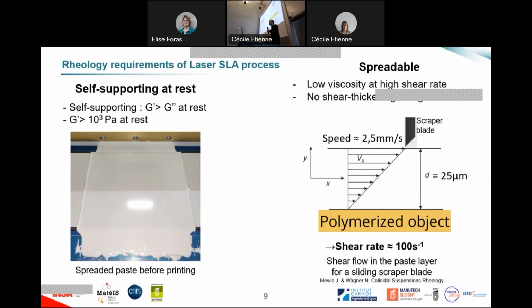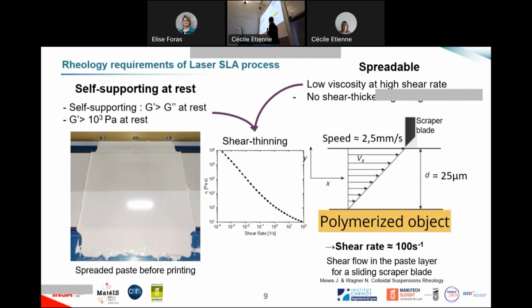We also want the paste to be well spreadable, so having a low viscosity at high shear rates permits this, and also avoiding shear thickening, because shear thickening is an increase of the viscosity at the considered shear rate, which is very high. The shear rate depends on the very small thickness of the layer and also on the speed of the scraper. So if we want to achieve a good spreading, we need a low viscosity at this shear rate. It means we want high viscosity at rest, low at high shear rates. So we need a shear thinning behavior, which corresponds to this type of behavior.